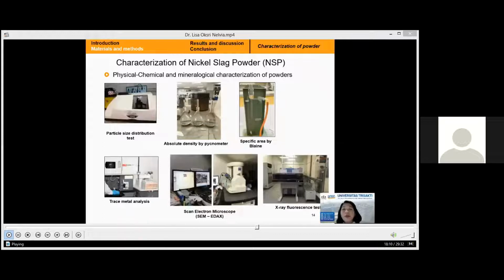Regarding the characterization of the nickel slag powder, we first studied the physical characterization by laser particle size, then the absolute density, and finally the specific area of the powders. We also did the trace metal analysis by atomic emission. Then the chemical composition of NSP was obtained from X-ray fluorescence by using an Epsilon 5 analyzer from PANalytical. Finally, to study the mineralogical characteristics of the powder, we used the scanning electron microscope.